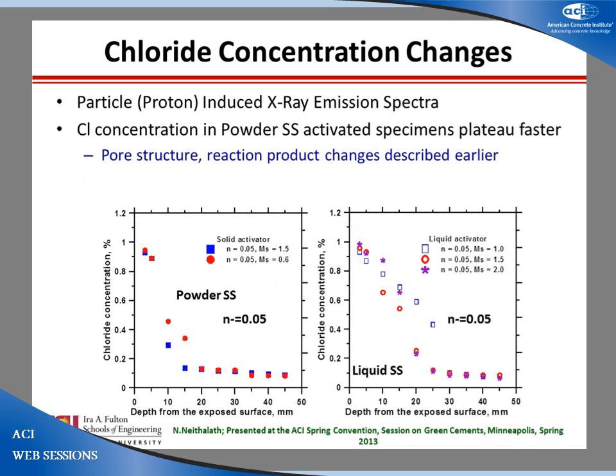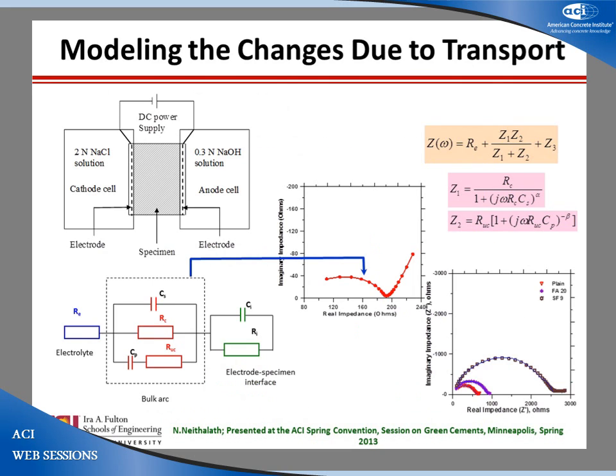You can see how for powder and for liquid, now this plateaus very quickly. This takes more time to plateau off. You can fit in a Fick's second law into it to calculate diffusion coefficient and a lot of other things from. And this is a very easy test because you take the entire specimen that was subjected to the test, just do proton emission at different depths and get the concentration profile.